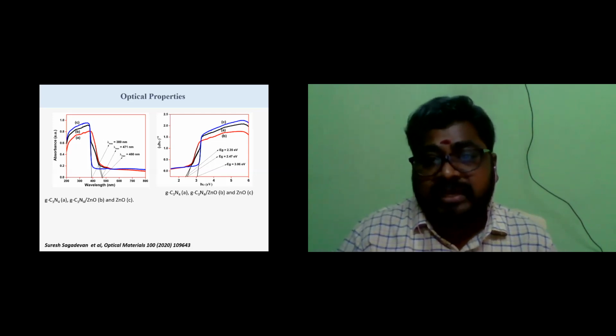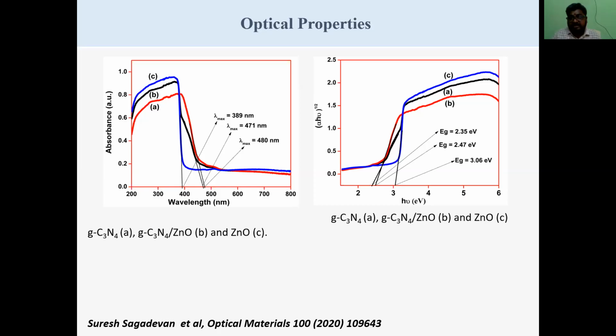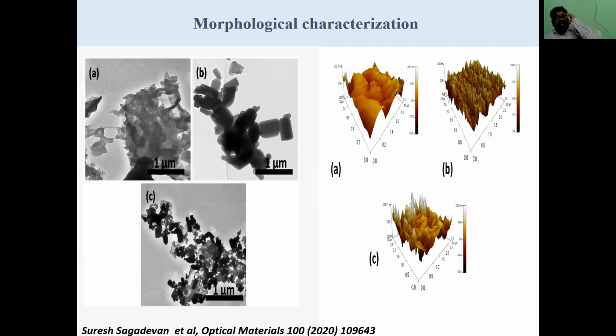And correspondingly, the next one is the band gap values, which we also calculated using the Tauc plot. The band gap value calculated for zinc oxide is 3.06 electron volt, and then for the composite material B, you can see here the band gap value is 2.47, and graphene carbon nitride is 2.35 electron volt.